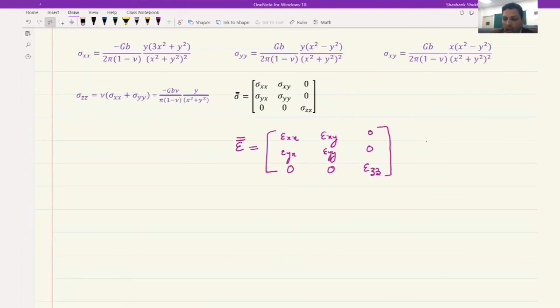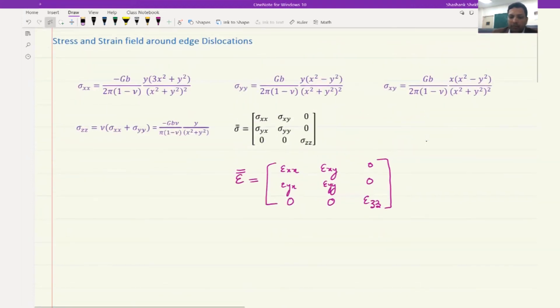The strain tensor for edge dislocation has similarly different non-zero components. If you wanted to plot how σxx varies along x and y axes, this doesn't have cylindrical symmetry, so we need not worry about cylindrical coordinates. The normal stresses σxx act along x. For an edge dislocation, we already know at a glance that there should be compressive stresses on the upper side and tensile stresses on the lower side.